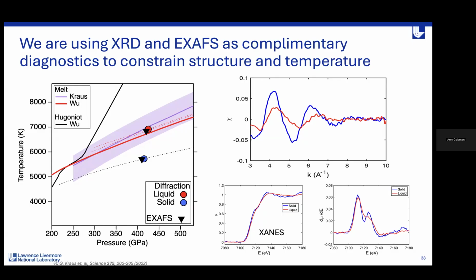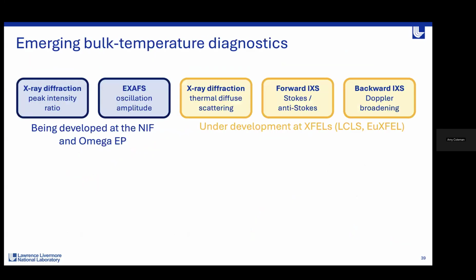And now the work begins to try and extract a temperature. This is very nice, very exciting. What we're hoping to do here is extend this up to much higher pressures. Presently we have data up to about just under 500 GPa. What we want to do is really look in this regime where these two melt curves diverge, so that we can comment on the difference between these two predicted melt curves based on in situ bulk temperature measurements. So very nice, very nice.